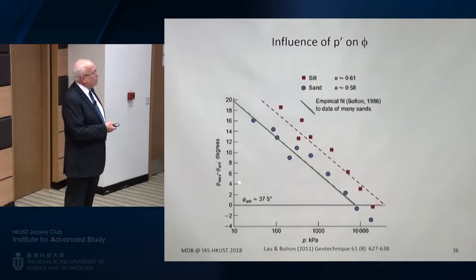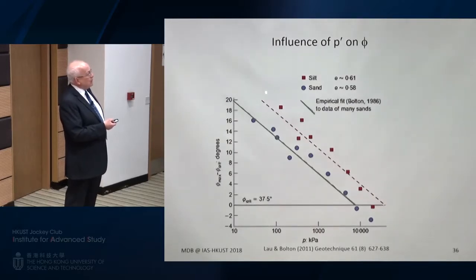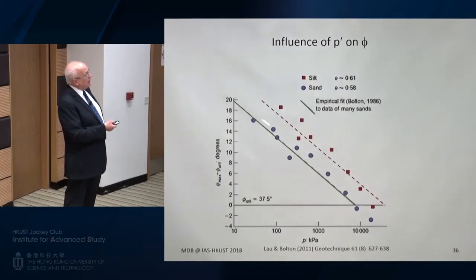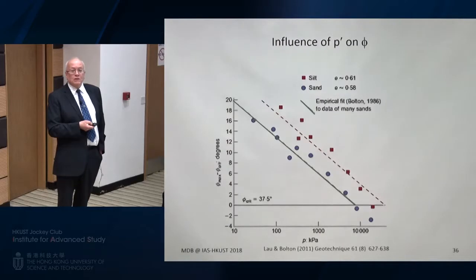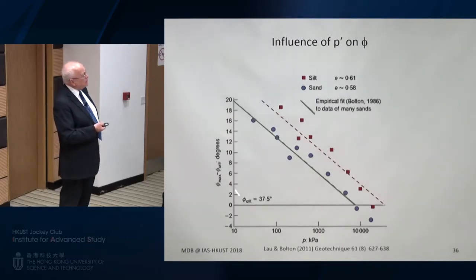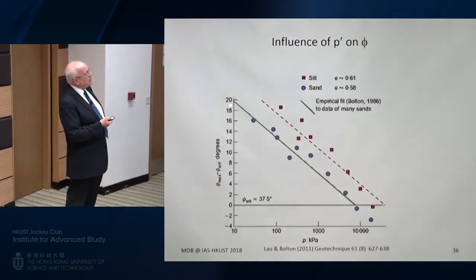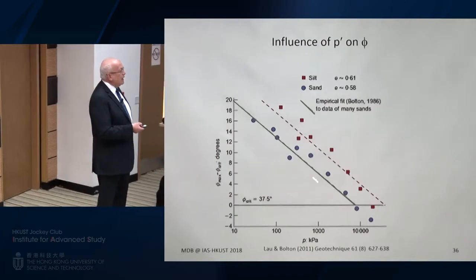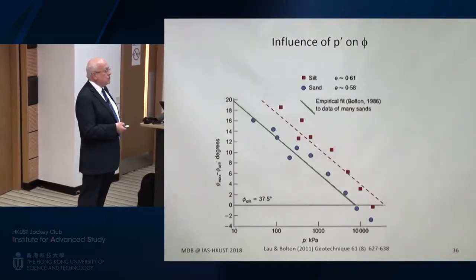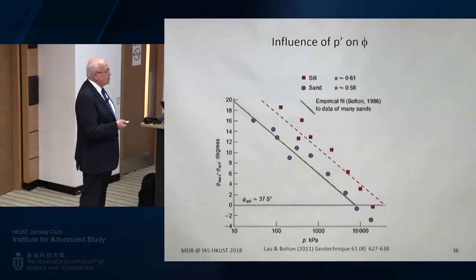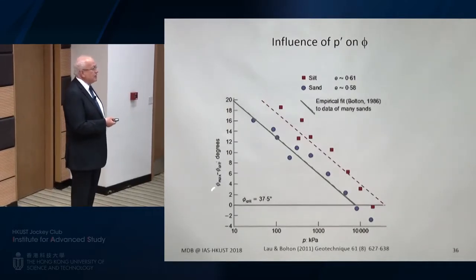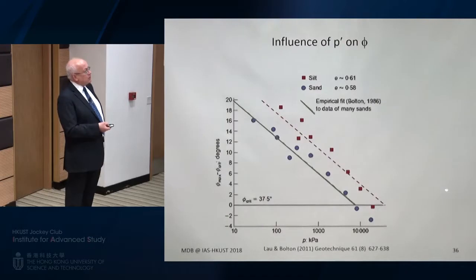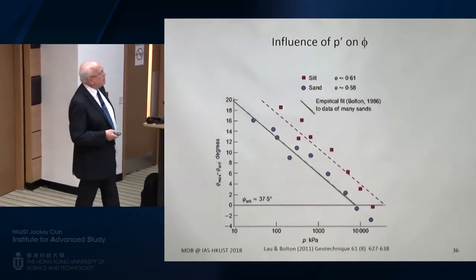But there's the data of phi of this quartz mineralogy, small particles, quartz mineralogy, sand-sized particles. The black line is the correlation I showed you 20 minutes ago from that 1986 paper. And so the Châtelet flint grit has a long name, but it just behaves like a sand. It's got quite a high phi crit because it's angular. And as you saw, it's got a dispersion of particle sizes. So you would expect its critical state angle to be high. And we believed that the critical state angle of both the sand and the silt was about the same at 37.5 degrees from that triaxial data I showed you.